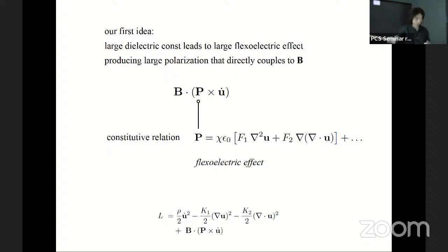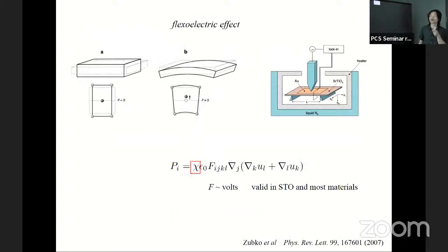Why is there such a constitutive relation? We can look at it in a more pictorial way. If you have a material that originally looks like this, with the positive and negative ions like this, and you bend it, then there will be a relative motion between the positive and negative charge centers. So that will generate a polarization. And when the dielectric constant is large, intuitively the positive and negative charges will more easily get separated. So that's why a large dielectric constant will generate a large flexoelectric effect. And you can measure this effect in STO. And indeed, you will confirm that there is a coefficient that is of the order of volts. It's the usual number; condensed matter things usually have a unit of volts. But then there's this large factor, which is 20,000 in STO.